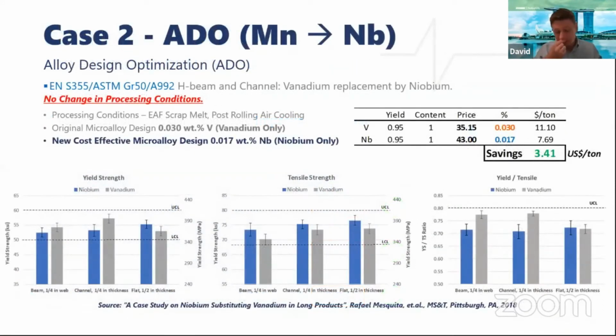Case number two was done in Gerdau, North America, also published. And it was a direct replacement of 0.03% vanadium, which was done with a target of 0.015 niobium, actual of 0.017 weight percent niobium. Considering the current alloy prices, that would give us $3.41 per ton, replacing for H-beams, channels and sections.